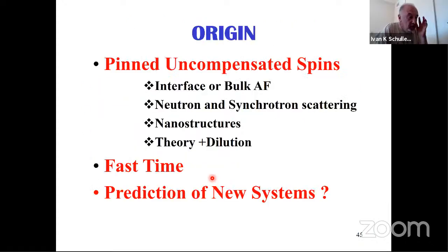Okay, so what I told you, why is this so complicated? The reason that this is complicated is because clearly the effect has to come from what are called the pinned moments. The effect has to come through the interface somehow. I don't know how, but somehow it has to come through the interface, obviously. And so there have to be some moments which are stuck, pinned, nailed down, uncompensated spins at the surface, although the surface nominally is compensated, but there are some defects. And so there have to be some pinned uncompensated moments at the interface. And then those are the ones that give origin to all this. And so that's what I want to tell you a little bit about, very little. I'm not going to tell you a lot about it.